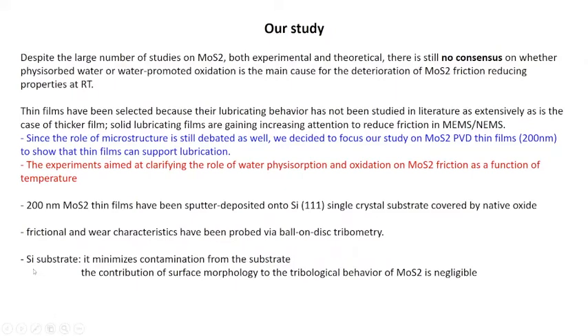We selected silicon as a substrate because in the form of single crystal, it presents a very flat surface, and so we can avoid the effect of surface morphology. And in addition, silicon is not a contaminant of MoS2, and so we can be sure that there is no effect of the substrate on the chemical characteristics of the coating.